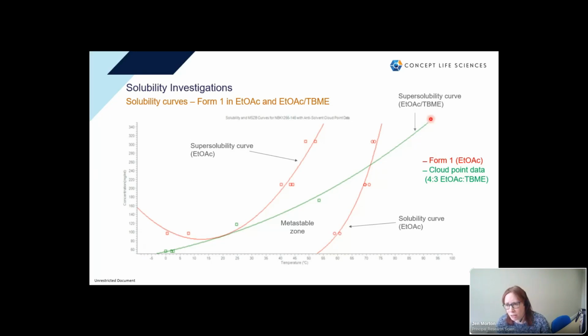And the green line that you see on this slide is that data. It's made up from the cloud points of that run. And that is overlaid onto the solubility curves that were just obtained in ethyl acetate. I think that what this shows is how much we are narrowing the metastable zone with the addition of antisolvent. And I suspect that means that when we were doing our original recrystallization, we were actually very close to the supersolubility curve, and we might have been veering into the unstable zone and getting some additional nucleation happening. Maybe that is the cause of our reproducibility issues.